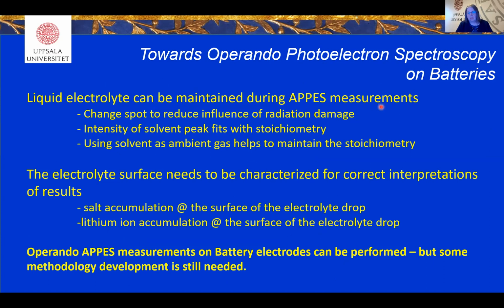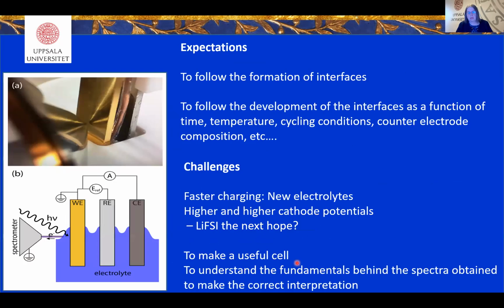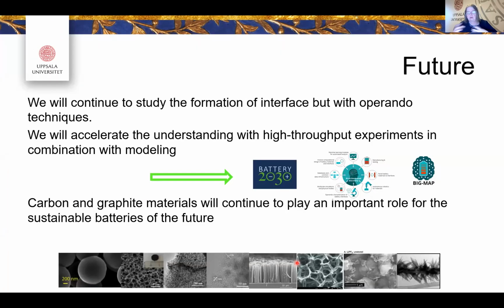And we can say something that we can see now. Liquid electrolyte can be maintained during the measurements. We have to change spots to reduce the influence of radiation damage. We need to characterize the electrolyte surface for correct interpretation of results. We have salts accumulated at the surface, and there is lithium ion accumulation also on the surface. And we can now perform battery operando measurements, but we are doing a lot of method development at the moment, and we are right in the process of publishing a paper on how you actually calibrate the peaks you find, because suddenly we are not at all at the same kind of thinking as we were with the postmortem studies. I hope that's something I can talk about another time.